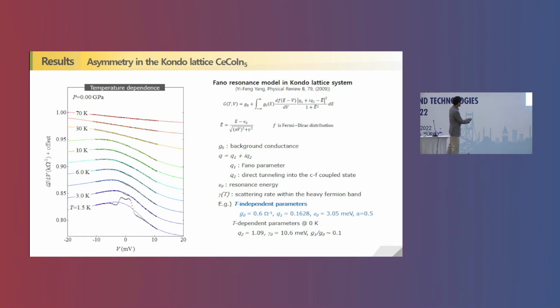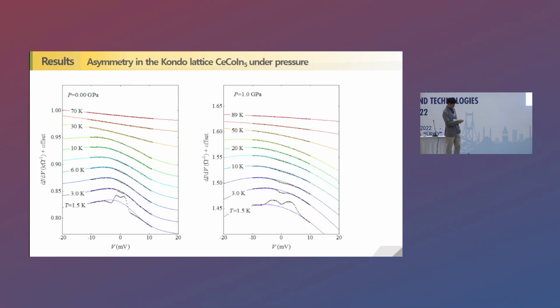So in order to fit these data sets, we fixed the background conductance, the Fano parameter, and the resonance energy, and even though we fixed them, it explains the data pretty well. This is the data set at 1.0 GPa, and the overall feature is pretty similar to ambient pressure. As you can see, the asymmetry becomes stronger with decreasing temperature, and at base temperature, on top of the background, you have Andreev reflection.